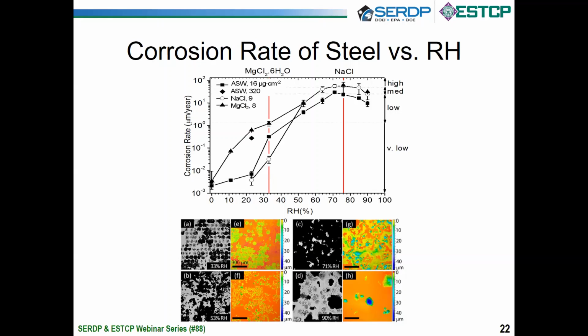When we design test chambers, typically we measure wet time and dry time. Now there are some chamber specs that call out a ramp time, and that's important because corrosion happens. The other thing I want to point out is if you look at these images on the bottom as a function of relative humidity, you can see the corrosion. There's the image and then the digitized image that was used to measure depth of attack. You can clearly see, as you go up in relative humidity, the difference in corrosion. In fact, at the subdeliquescence point at 70% humidity, the corrosion has fairly well covered the surface. So you can see its value of attack based on here.